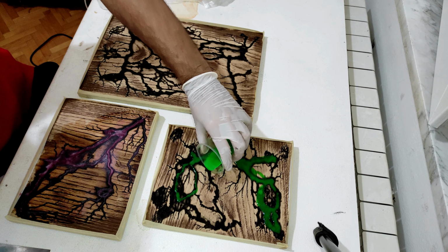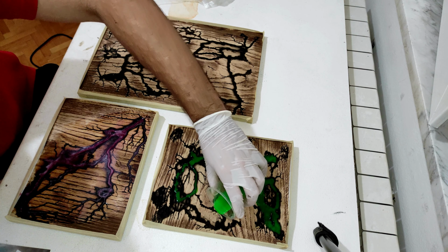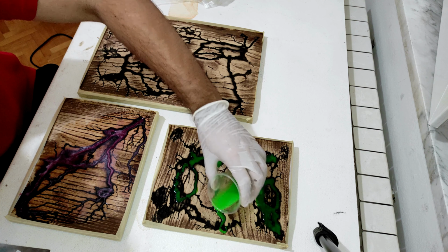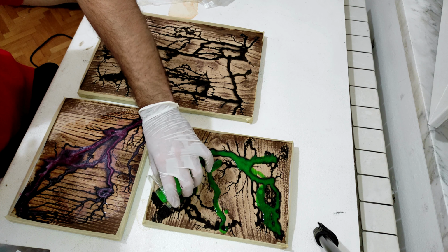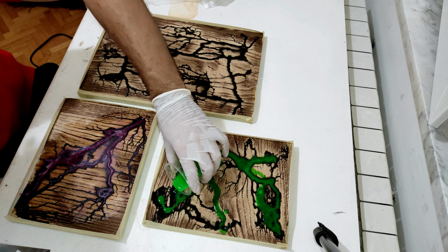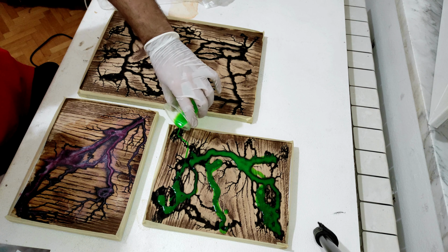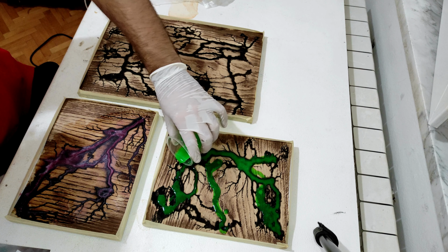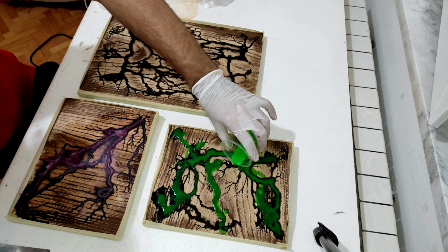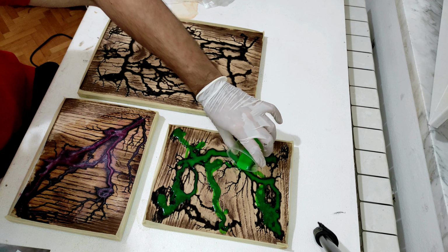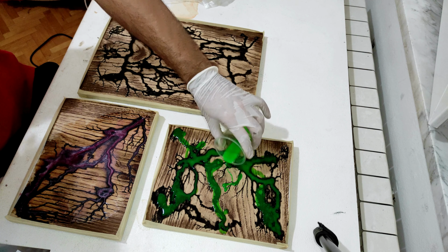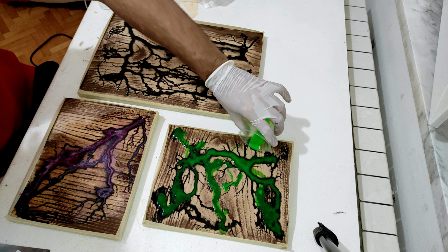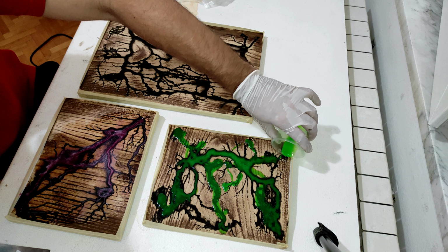Depending on the epoxy, resin, and curing agent used, room temperature curing adhesive formulations can harden in as little as several minutes at room temperature, but most systems require from 18 to 72 hours to reach full strength. The room temperature curing epoxy adhesives can also be cured at elevated temperatures if faster curing times are required.